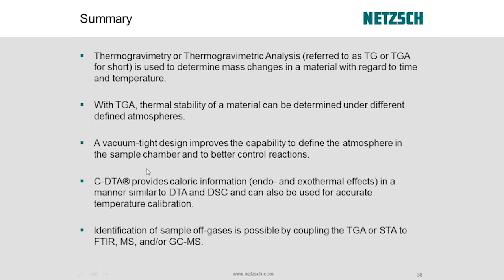I want to reiterate this point. The vacuum-tight design improves the capability to define the atmosphere in the sample chamber and to better control the reaction conditions. So remember that example I showed you of the polyethylene liner with the carbon black. If you have any oxygen leaking in from the outside, if you're using a so-called gas-tight system, there's a good chance that oxygen is going to be still hiding in there somewhere. All the NETZSCH instruments are supplied with a vacuum pump and they're vacuum tight so that we can pull down that chamber and then backfill with very pure gas atmospheres to control the reaction conditions. You can even run in a vacuum. We've got some folks who do experiments to look at mass behavior in a vacuum itself. So a vacuum tight design has a huge advantage in terms of controlling the gas atmospheres.